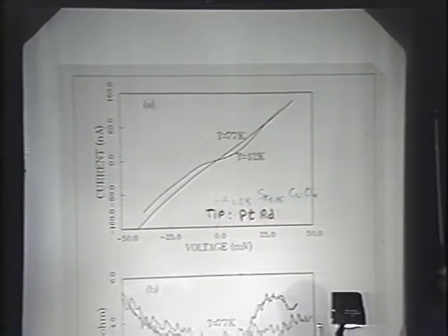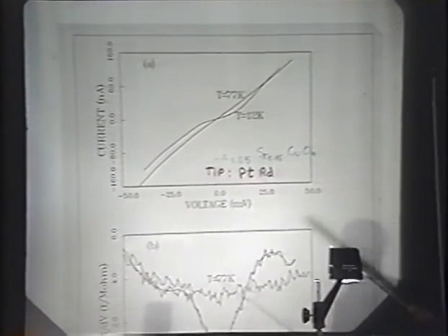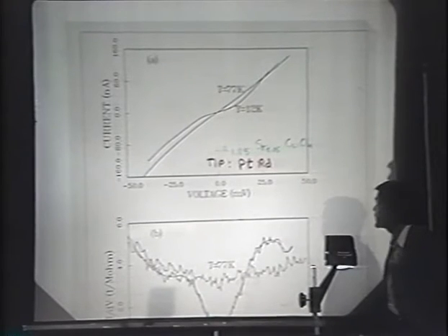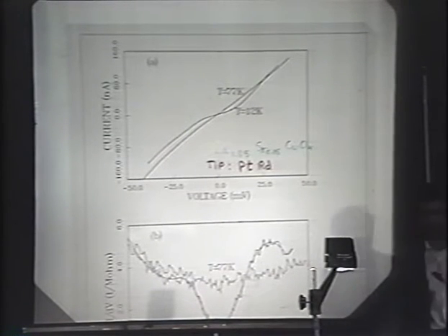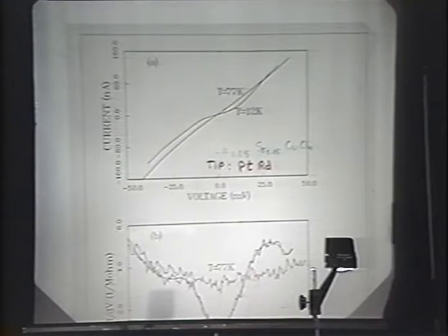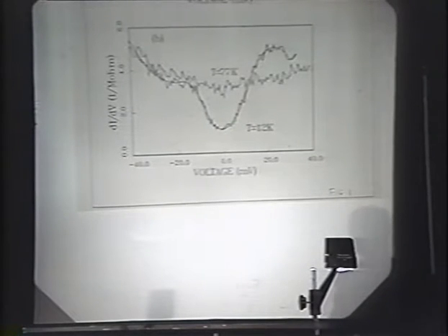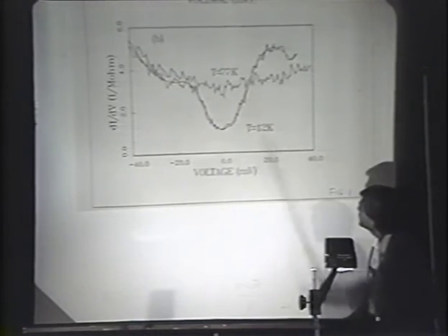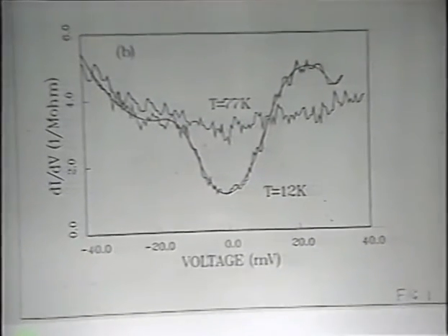First thing that we saw were IVs like these. And here I'm showing IVs at two different temperatures, at 12 Kelvin and 77 Kelvin. In this case, the STM is in vacuum, so it's not at 4.2 Kelvin. The sample is lanthanum strontium copper oxide with the right composition for maximum TC. Very sharp transition, 1.1 degrees wide, and an onset of 40 degrees Kelvin. The tip in this case was platinum rhodium. If we take a numerical derivative of the above data, it's easy to see then that you could point your fingers at something that looks like a superconducting gap there.